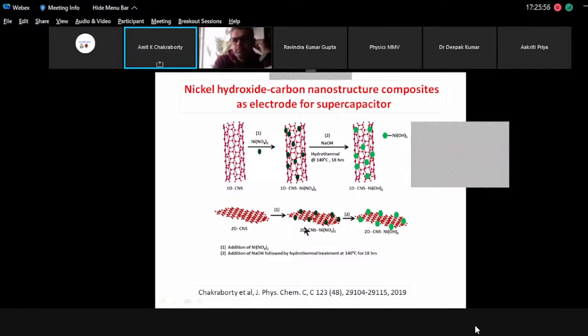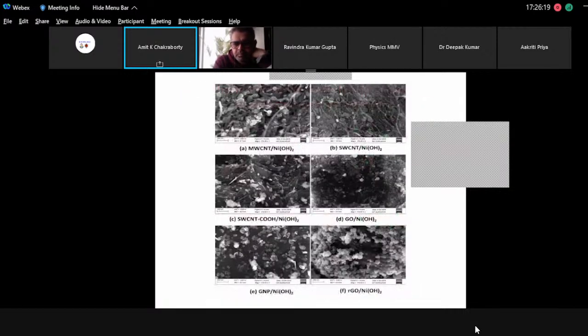Okay, so these 6 different carbon nanostructures we chose by taking the same weight fraction, roughly 6 to 7 weight percent of carbon nanostructures, and the rest we combined with nickel hydroxide, the same material that we have studied earlier. So nickel hydroxide was combined with 6 to 7% of carbon nanostructures, and then we tried to see which composite performs the best. Because in the literature, people have often claimed that by putting carbon nanotubes we get this much of increase.